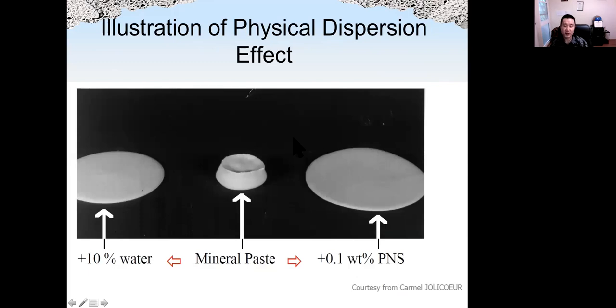So water reducing agent can not only work on cement, but other types of mineral can also be well dispersed using these chemicals. As you can see from here, this is a type of mineral paste. This is when we add 10% more water, it becomes well dispersed. But this is 0.1% by weight of the paste, with one type of water reducing agent. We can see even more dispersion compared with 10% more water.